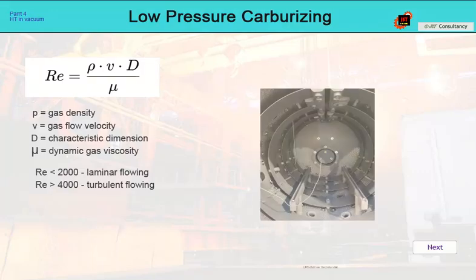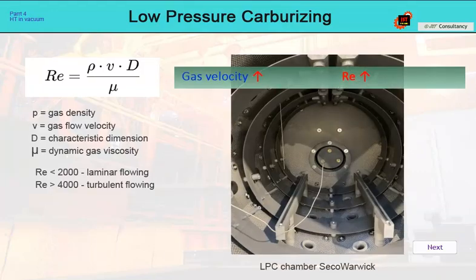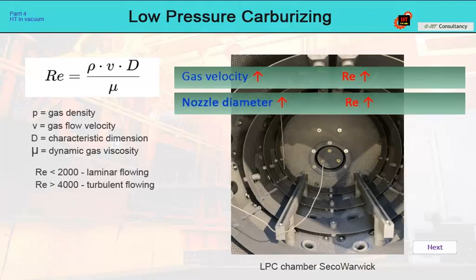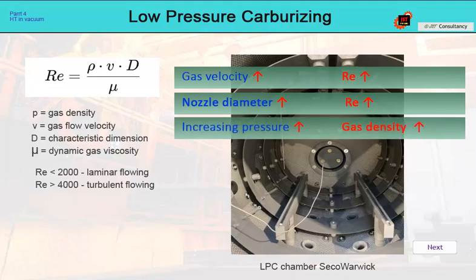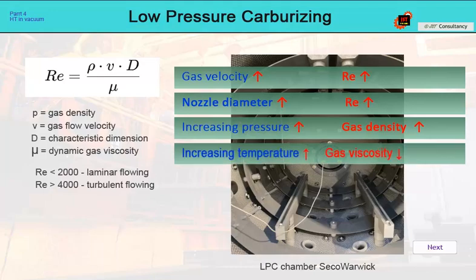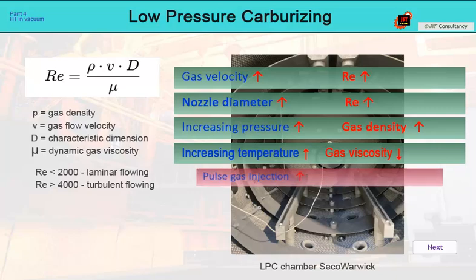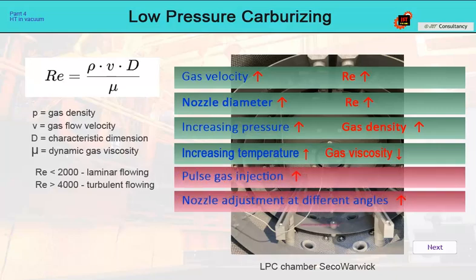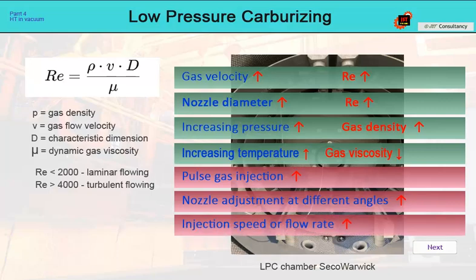However, the diameter of the nozzle will determine the flow rate of the gas, and this cannot be increased indefinitely because it must be in balance with the furnace's pumping system. Another effect is the effect of the density of the gas, but it will decrease with decreasing pressure, and it will also be necessary to take into account the influence of the viscosity of the gas, which will decrease with increasing temperature. Since turbulent flow is physically difficult to achieve under the pressure and temperature conditions of low-pressure carburizing, other means must be found. For example, pulse gas injection, nozzle adjustment at different angles, or increasing injection speed or flow rate can help.